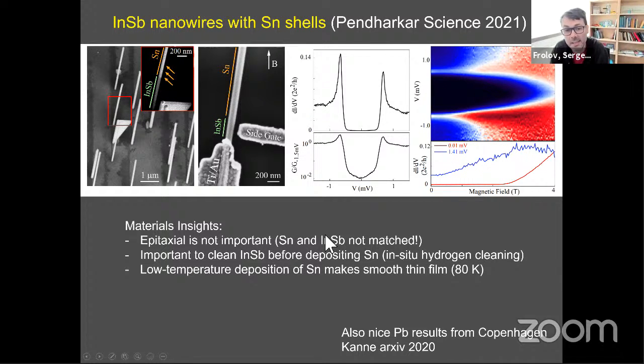But one of the most surprising things we learned from this is that tin and indium antimonide lattices have no relationship in our case. Actually, tin and indium antimonide are lattice matched when it's alpha tin, but alpha tin is not superconducting. So beta superconducting tin is not meshed. And the shell is granular and all kinds of imperfect, but still gives good data. So maybe this epitaxial relationship, the match between crystal lattices, is not crucial to see things like this hard gap.